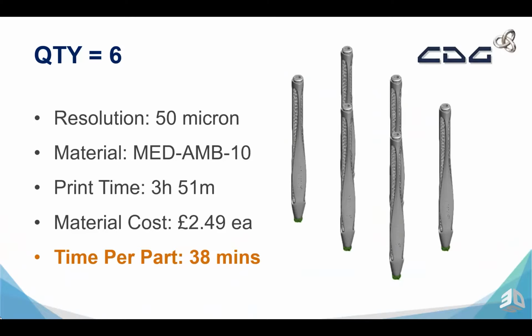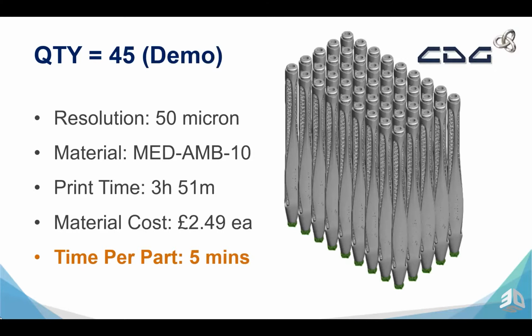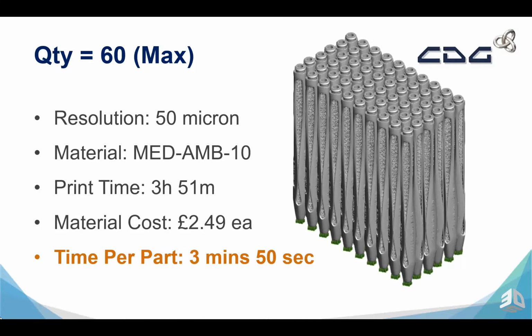So this is a really good idea of what we can achieve with just a small amount of production. So let's see for this demo, what did we spend on each pen? So 50 microns, 3 hours 51, £2.49 each, 5 minutes per pen for 45 pens. This is a very nice sparse amount of pens really. So what can we do to maximize the build envelope? So let's see, we can put 60 into the build envelope. So this reduces the time down to 3 minutes and 50 seconds per pen. A really, really quick process.